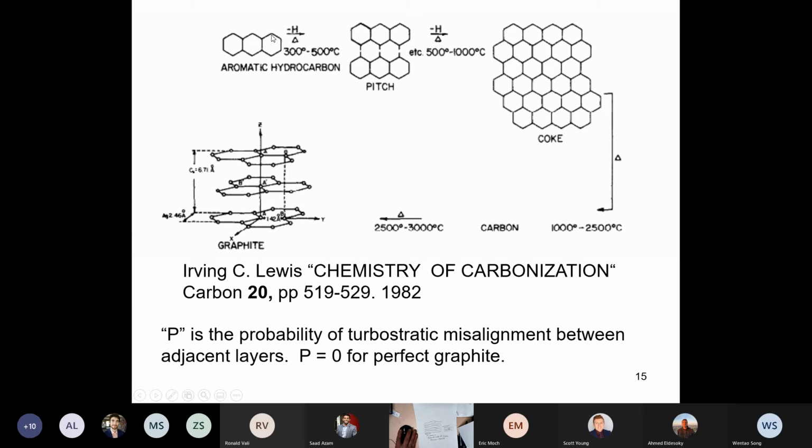So this molecule here has hydrogens not shown at every vertex. There's a hydrogen atom not shown, so you'd have to count the exposed vertexes. It looks like 10 hydrogens for 3 rings. And as you heat more, you get more hydrogen loss and more rings join together. So you would have less hydrogen per carbon in this bigger molecule.